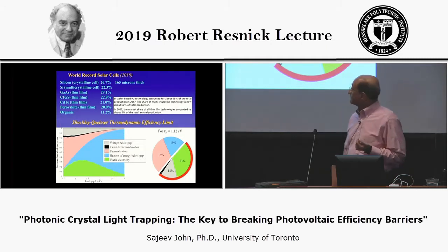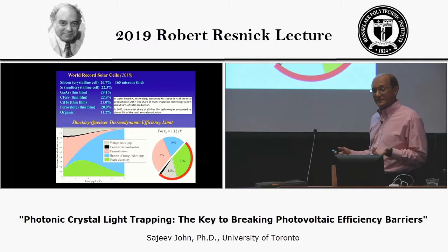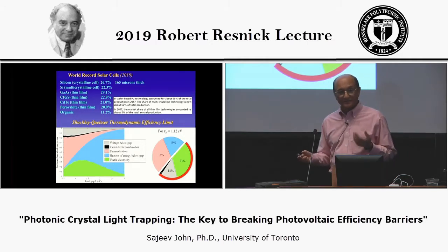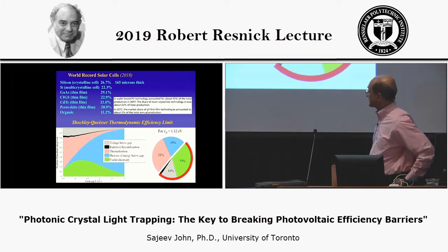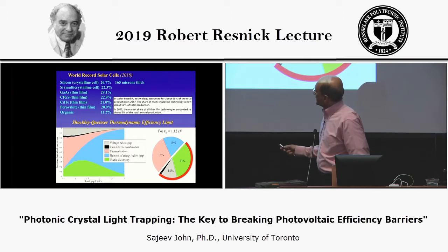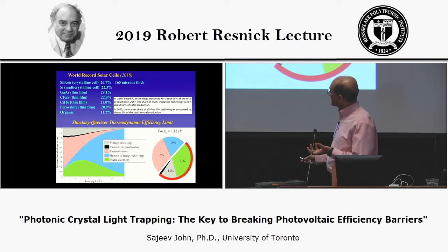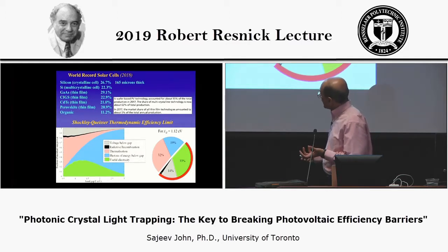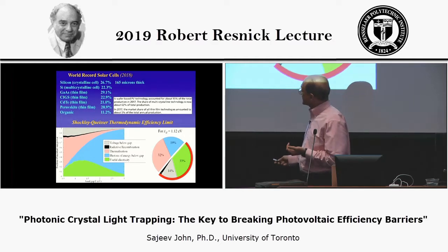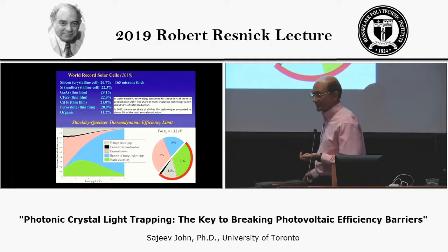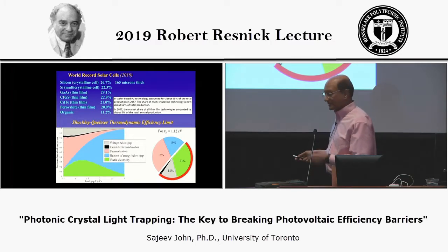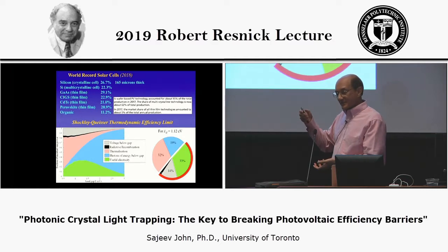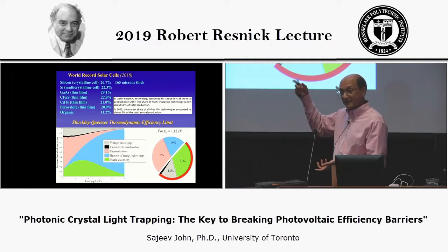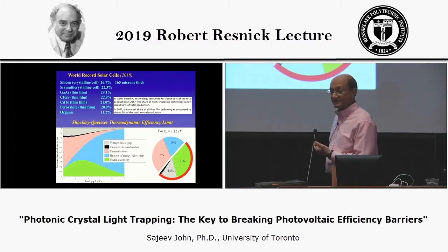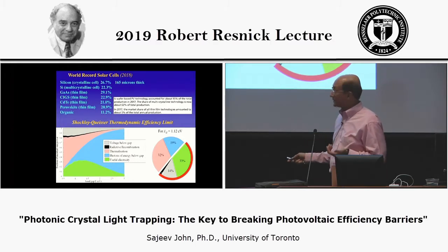Now, many years ago, two famous scientists, Shockley and Queisser, defined some of the limits to the efficiency of solar cells based on the nature of the semiconductor band gap associated with the material. So what I've plotted here on the vertical axis is where the energy that's being absorbed by the sun ends up as a function of the band gap of the semiconductor under consideration. So the red region, the pink region here, corresponds to a material with a relatively small band gap. So there are photons from the sun that have a much higher energy than the band gap energy. They create a high energy electron hole pair, but the electrons then scatter and relax to the band edge energy, and all that excess energy is given off in the form of heat.